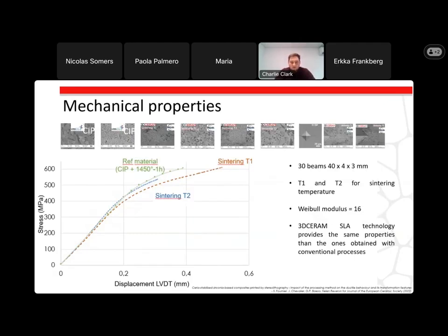So once we had this powder, we made the formulation, and we made some test parts. We printed some different beams for testing the mechanical properties. We used 2 different sintering temperatures just to see how much of an effect a 50 degrees Celsius variation of the sintering temperature had on the results. With the results that we obtained, we had a Weibull modulus of 16, which was very interesting for us because it meant that the defects were uniformly distributed across the bars, which meant that the printing was very homogeneous across the build plate and the parts were repeatable.